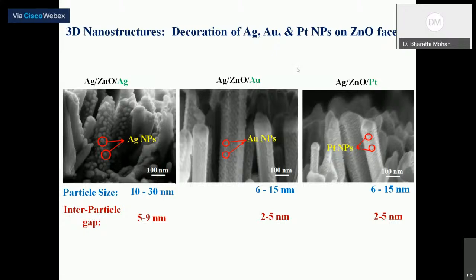The reason for the bigger particle size and higher interparticle gap in the case of silver is that silver is deposited using a thermal evaporator, whereas gold and platinum are deposited using sputtering techniques. So therefore, you could see some change in the particle size as well as in the interparticle gap.